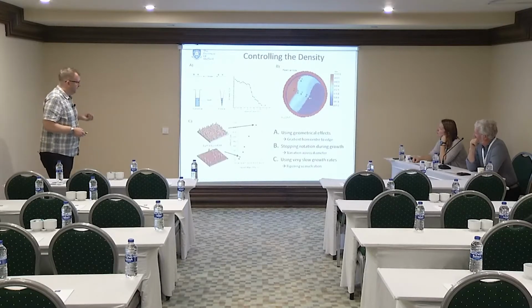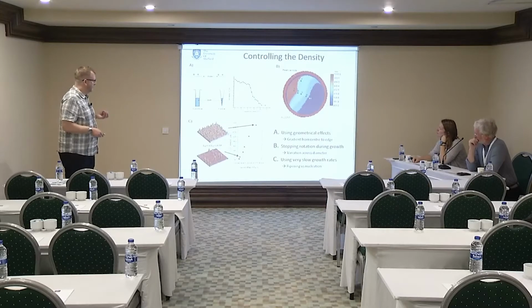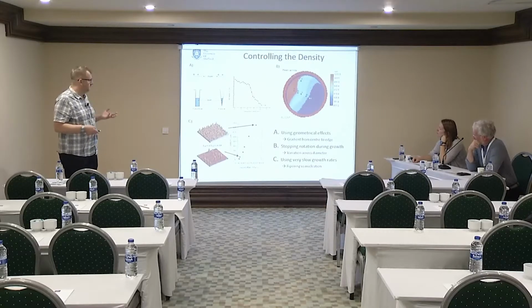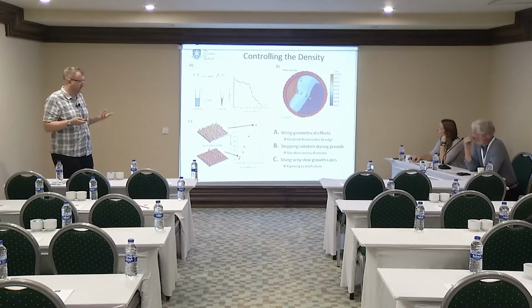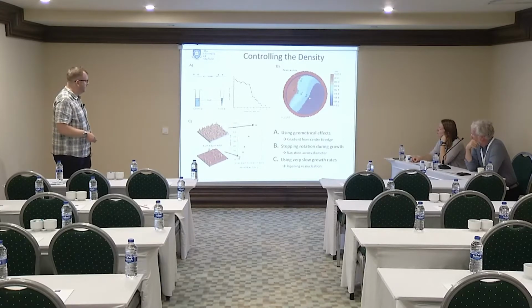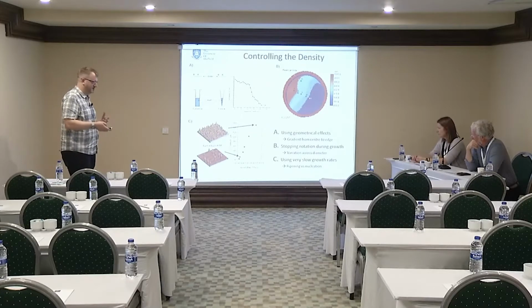Or we can go to extremely low growth rates. So this is dropping the growth rate down by a factor of 100 or so, meaning we grow these 2 monolayers in about 15 minutes. That gives us very low densities and very uniform. And we have this competing ripening versus nucleation.